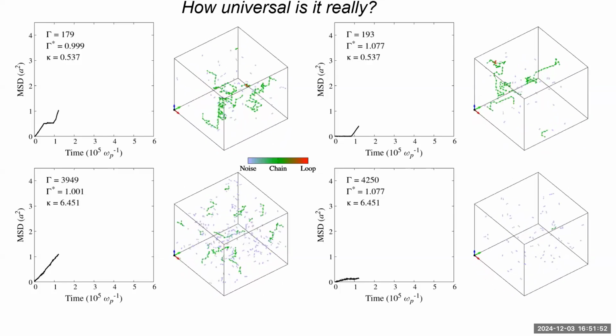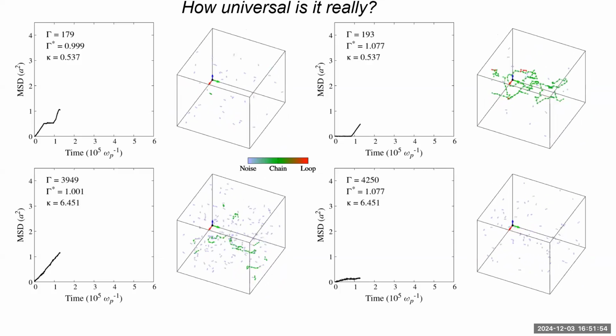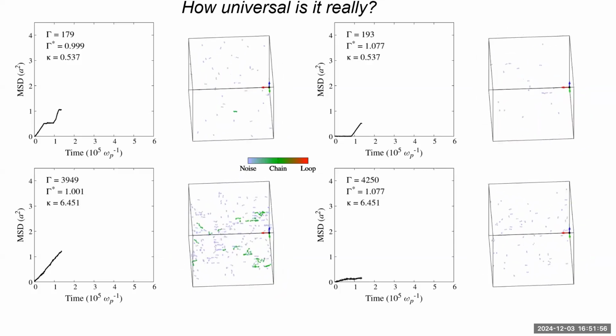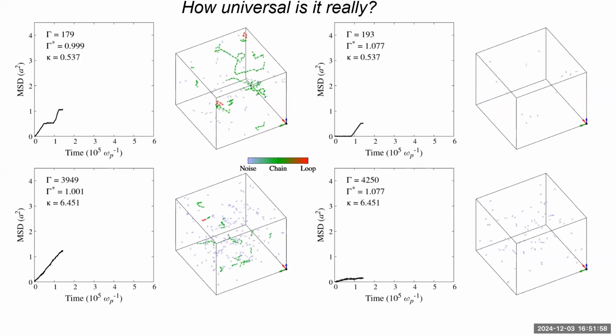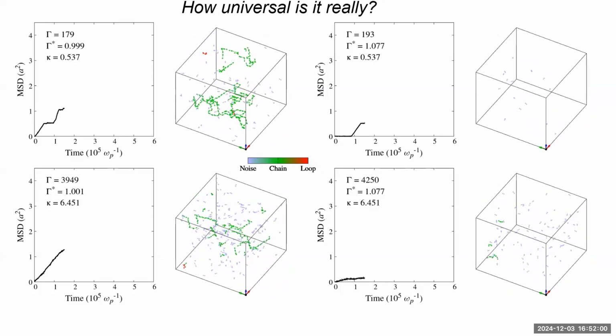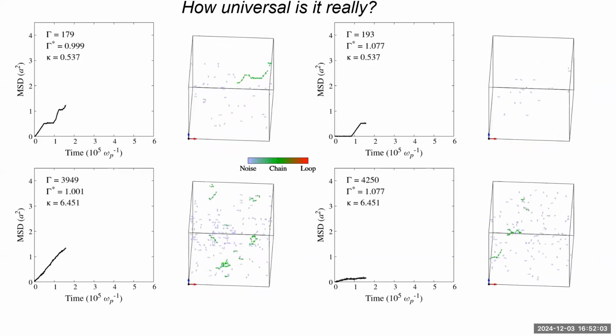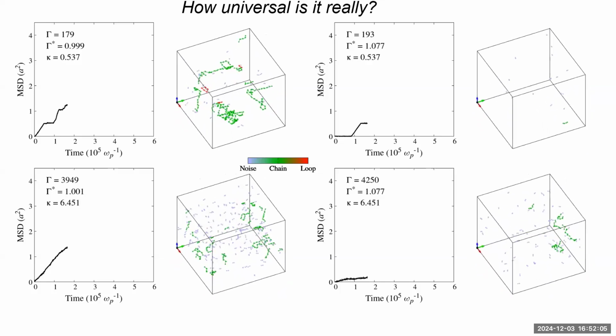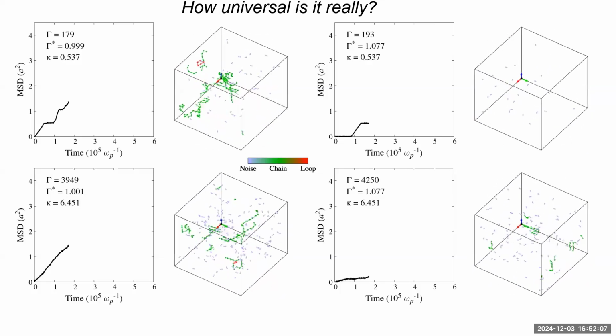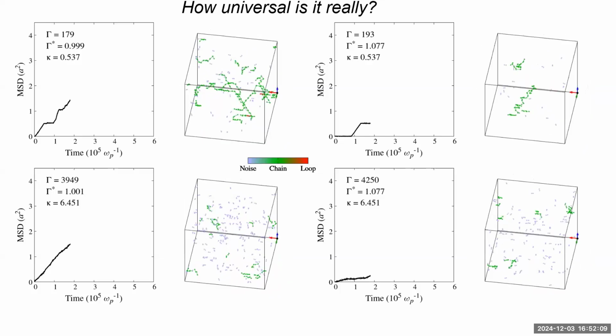And sort of these 2 effects, the average number of defects, the sort of activation energy to form a defect, and then the activation energy of defect migration, even though they're different and they scale differently, they come together to get you the same mean diffusion coefficient. My point is that the work is never finished. There's always another interesting thing to unpack.